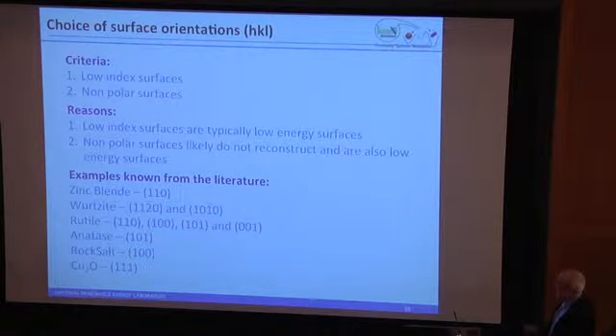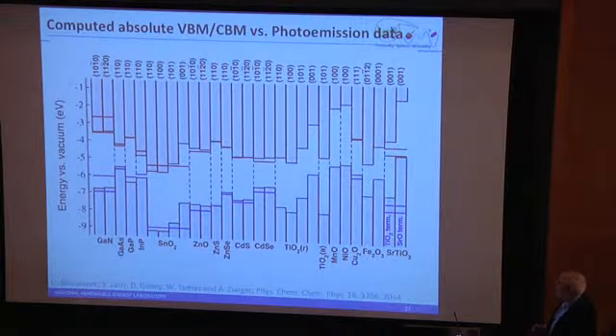And so from the literature, this is some of the orientations. And then what we can do is we can plot these all as a function of surface orientation, the experimentally measured, so this is versus photoemission data. It's too bad Antoine isn't here because he could tell me where some of the missing data is. So the photoemission data is the bars, and the calculated numbers are the solid lines. And the first thing you notice is that it's actually pretty good. The agreement is actually pretty remarkable.